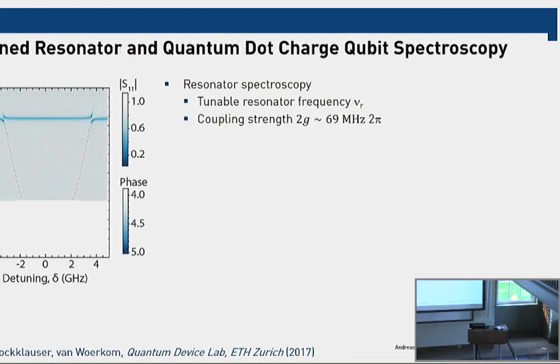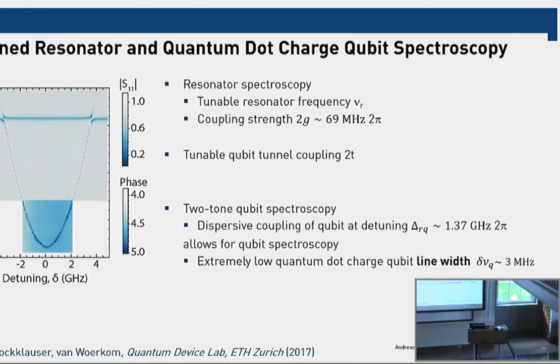You can also repeat this spectroscopy measurement, which is shown here. So this is the resonance frequency of the cavity with the 2 anti-crossings. And then you can do this 2-tone spectroscopy technique to again spectroscopically measure the transition frequency of this double dot charge qubit. Now what we've seen in this particular device is that we get charge line widths which are 3 megahertz or so, which is about 100 times smaller than what we've seen in our early devices, and which is now definitely well below what people would have expected should be possible in these devices.